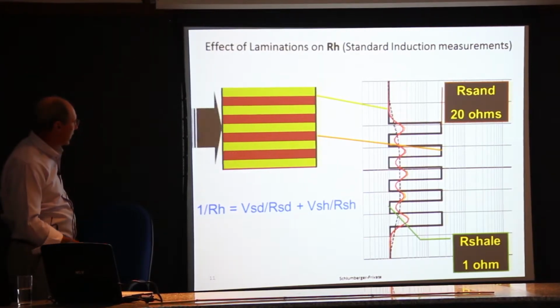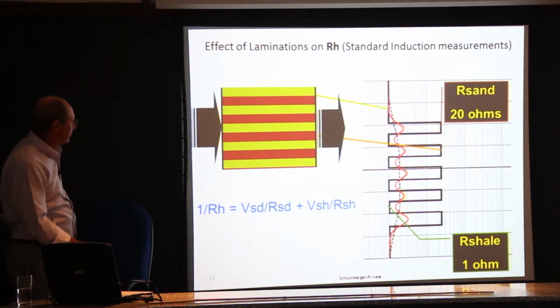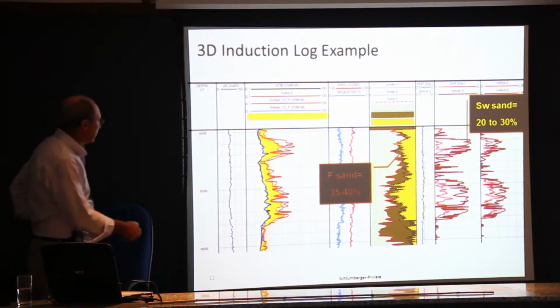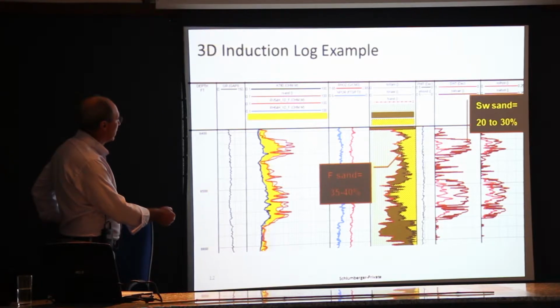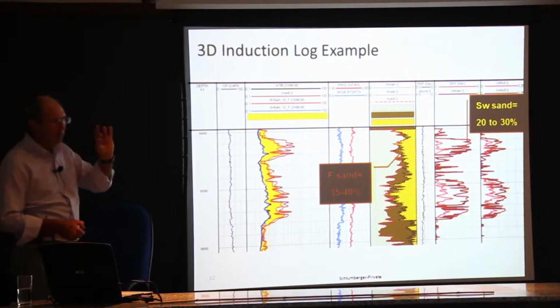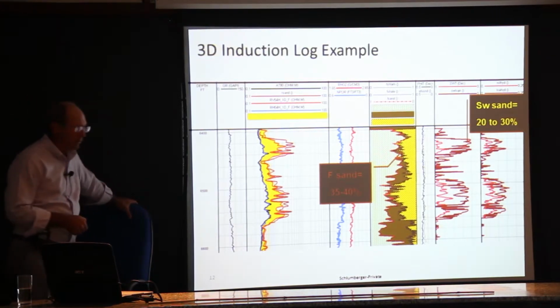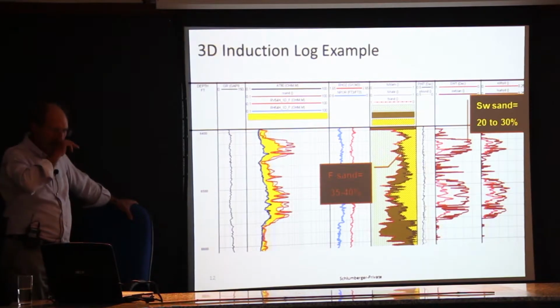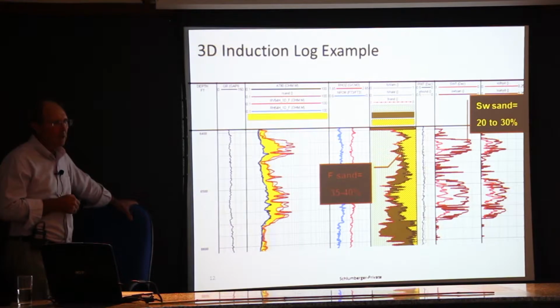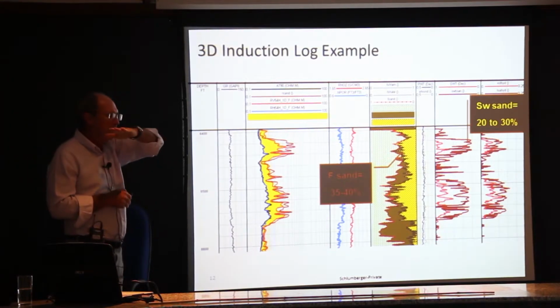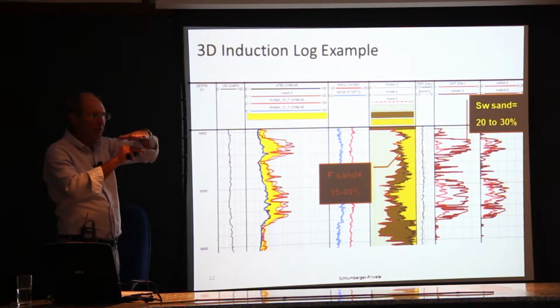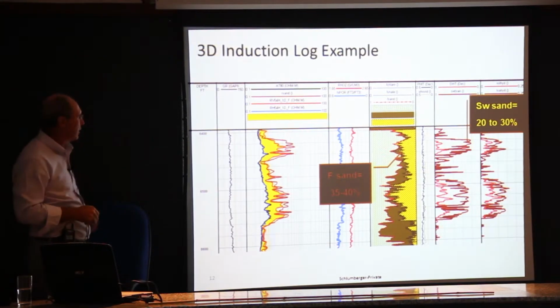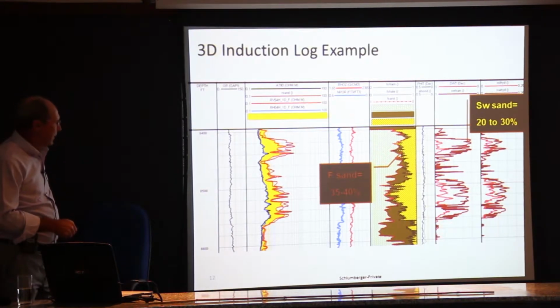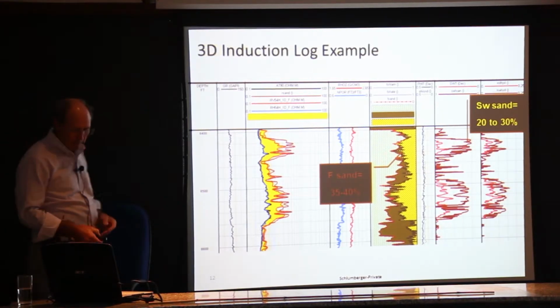But if we go to a triaxial one, you will see this is the horizontal resistivity, and these are the vertical resistivities here, out here, because they're responding to those oil-filled sand layers. And we do see this type of situation occasionally in the pre-salt. They're in carbonates that are called laminites, where you have these sequences of muddy carbonate shale with some higher porosity carbonate that could have oil in it. So this is useful in some parts of the pre-salt.